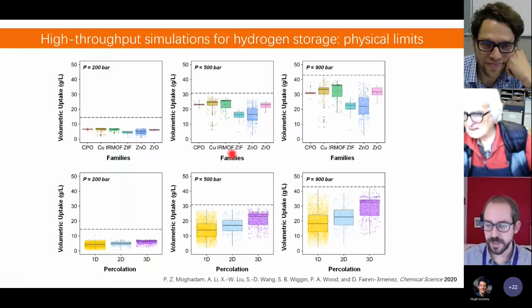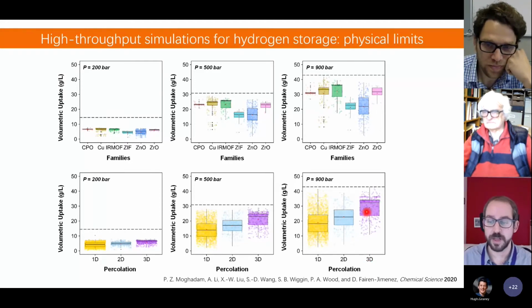You can see the representation here. Every single sphere, every single point is one metal-organic framework. On average, this is what we are trying to represent here. On average, 3-dimensional porosities will have higher uptakes than 1-dimensional, but at the same time, you have a lot of MOFs that will have higher uptake for hydrogen, 1-dimensional higher than the 3-dimensional. These materials, for example, are going to have higher capacity than all these ones that you have here. This is what we have observed also for hydrogen.